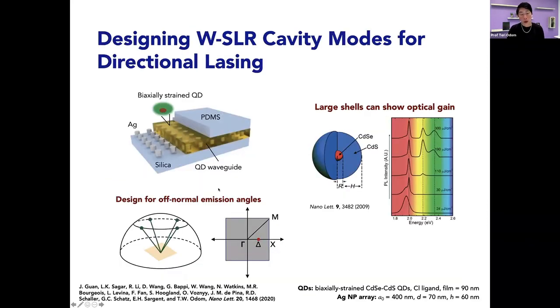And we can also use this type of system to achieve directional lasing. And so this is the system in this case with a PDMS on top. And we use these core shell with very large shells. And the shells usually do not provide enough gain, and that's why mostly the emission is from the core. But if you pump hard enough, you can see gain from both. And so we use this system.